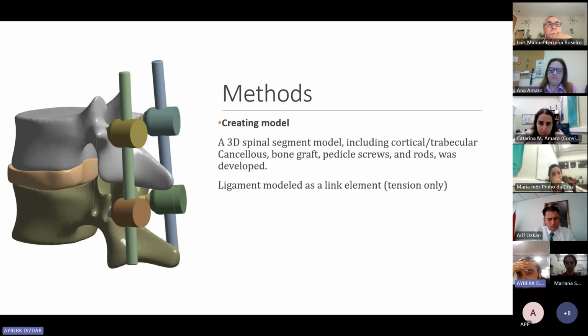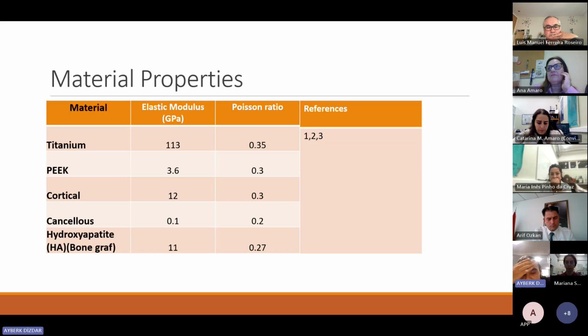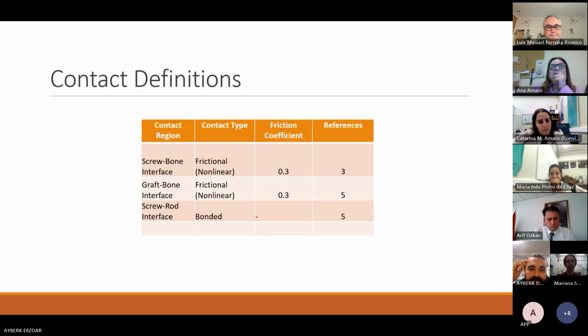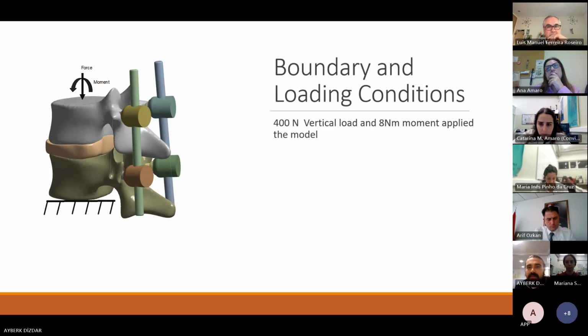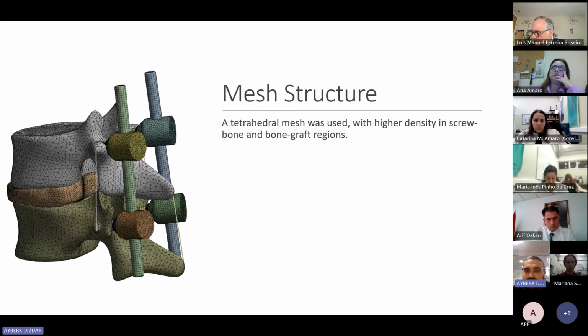Creating the model: a 3D spinal segment model including cortical bone, trabecular bone, cancellous bone, bone graft, pedicle screws, and rods was developed. The ligament model used link elements, modeled as tension only. We took the material properties and the contact definitions from the literature. The screw bone and graft bone interfaces were assigned as frictional contact, and the screw rod interface was bonded. Boundary and loading conditions: a 400 Newton vertical load and an 8 Newton meter moment were applied to the model. A tetrahedral mesh was used with higher density in the screw bone and graft regions.